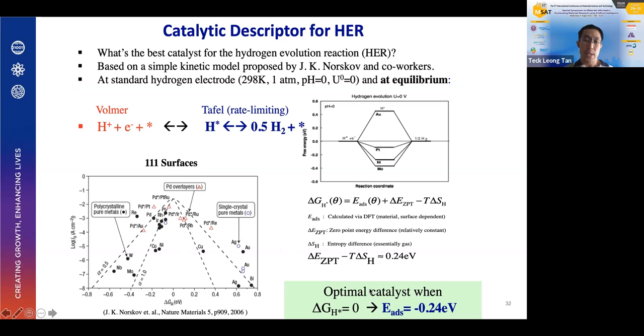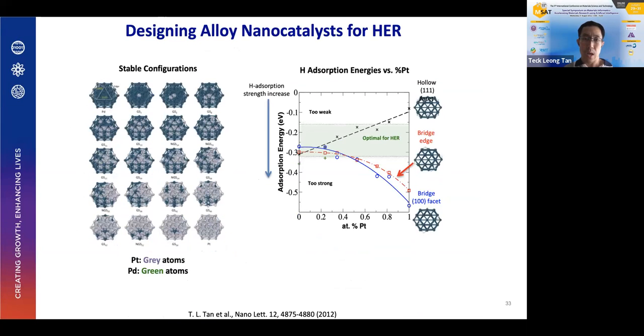For computational researchers like me, what we need to do is to find a catalyst which can absorb the hydrogen atom in around this absorption range of negative 0.24 eV. So we can use this to design new catalyst materials. What we show here is that if we look at platinum and palladium nanoparticles as an example, in the diagram on the left, we can use this kind of machine learned surrogate model to identify what are the stable core shell structures of palladium and platinum.